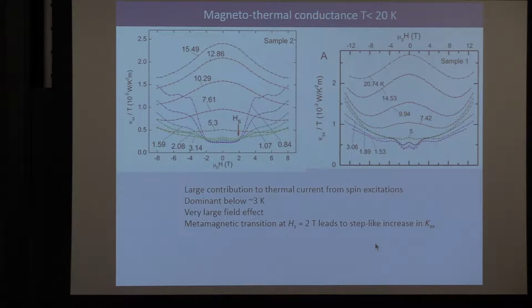So before we do that, we can measure the kappa XX, the thermal conductivity in a magnetic field. And when you get to low temperatures, at high temperatures it's flat. The magnetic field has no effect on the thermal conductivity. But below 10 Kelvin or so, you start to see changes. And at very low temperatures, it has a very poor thermal conductivity, but rises immediately at about 2 Tesla.